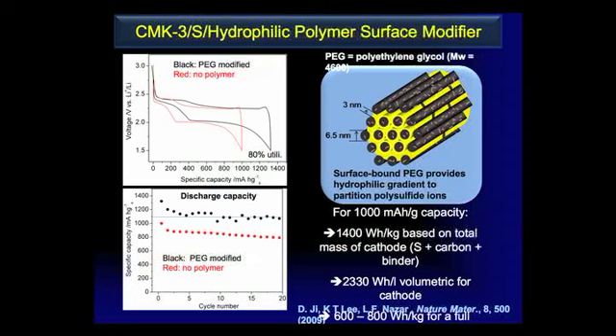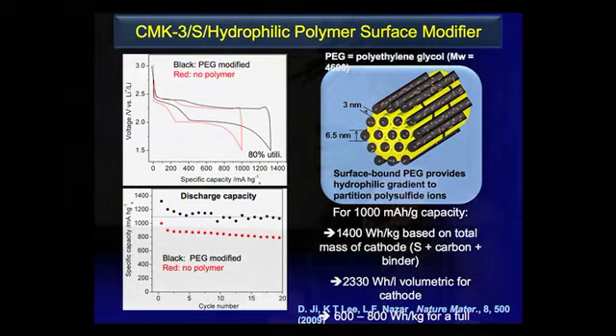We have polymer coated these materials with polyethylene glycol, and we find that this effectively completely inhibits this deposition of the glassy sulfides on the surface, for a variety of reasons. One is that they're insulating, and the other is that they act as a hydrophilic gradient. If we divide this by half, which is a typical fudge factor, we would be looking at about 600 to 800 watt-hours for a full cell. And the question then is how to get this capacity cycling for a long period of time.